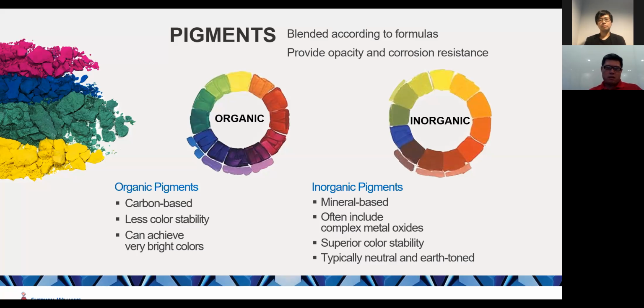Now, inorganic pigment is different. Inorganic pigment is mineral-based and often made from metal oxides. So the color is not as bright as the organic pigment, but the color stays very stable, all right? When you're talking about long-term, a 20-year warranty or 35-year warranty or whatever, this pigment will stay very close to the original color. So if we're using the inorganic pigment for your projects, we don't normally have to use the 3-coat system. A 2-coat system can meet the requirement for your project.